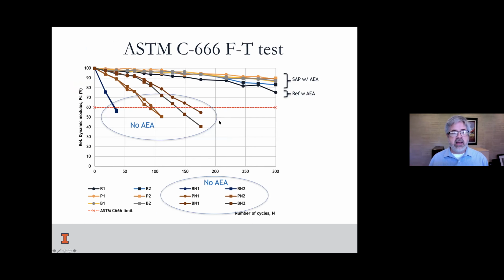The data that I have here shows that we had some samples with no air entraining admixture, and then the same materials with air entraining admixture up here. Yes, the SAPs outperformed the reference with air entraining admixtures. So all of them were okay. All of them stayed above the threshold in the 666 tests. But when you don't have air entrainment, they all failed at some point before 300 cycles.